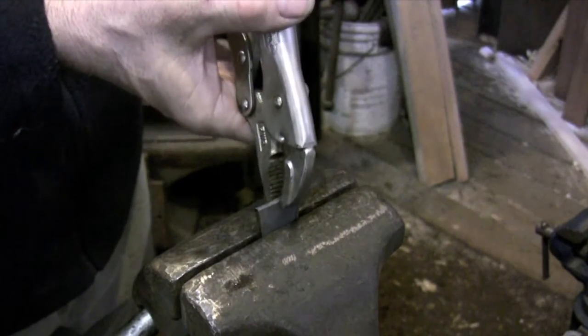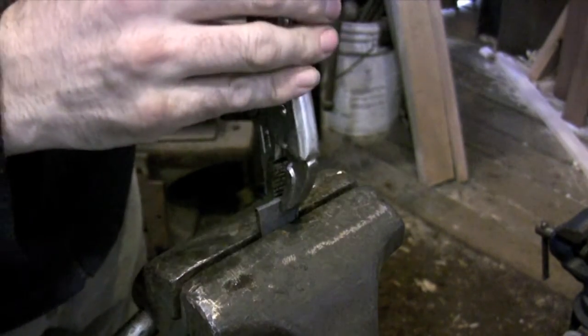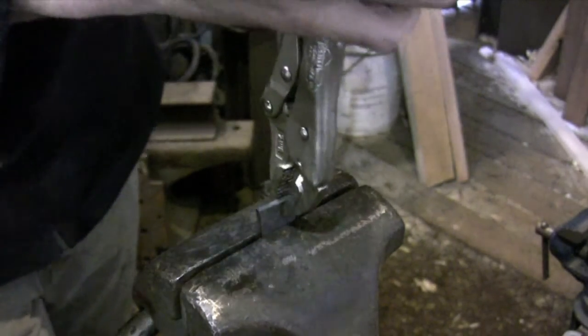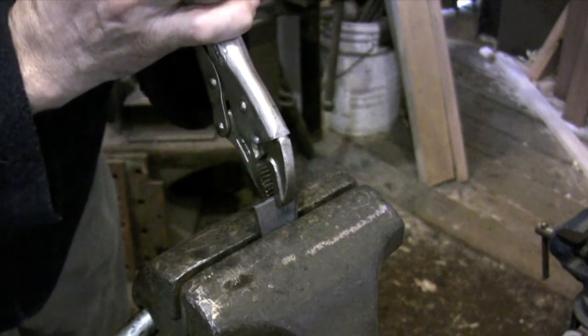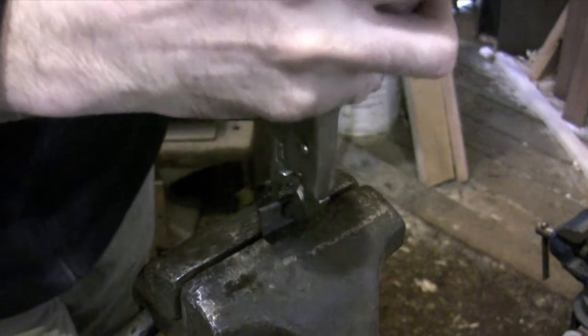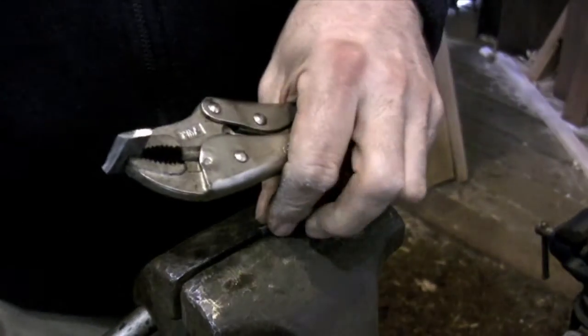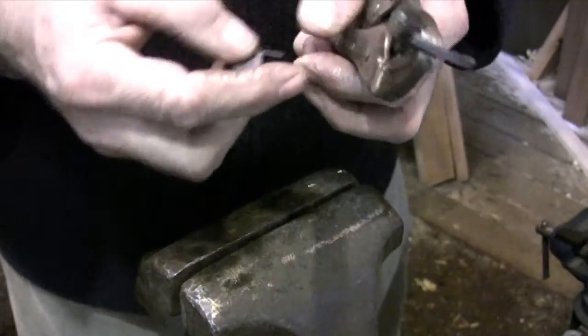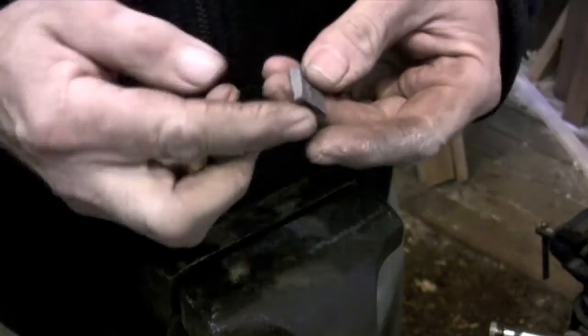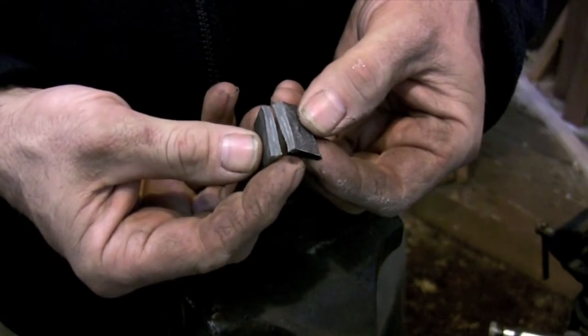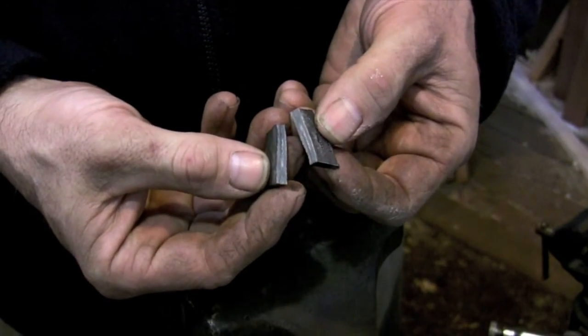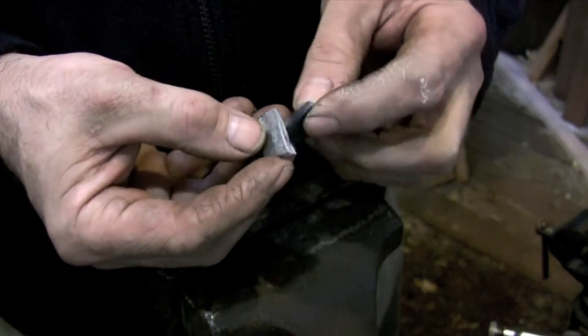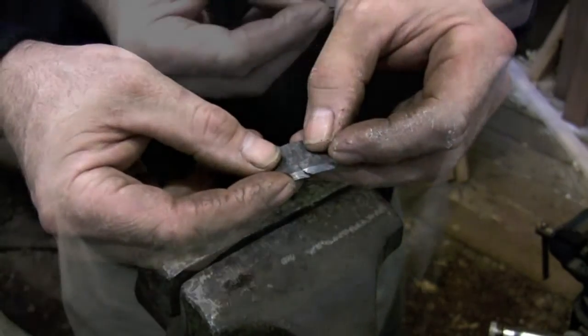The second sample piece with two forge welds offers quite a bit more resistance. The weld is actually strong enough that I need to bend the sample before the weld will break. But like the first sample, it breaks cleanly along the weld line, and it's obvious that the welding process hasn't been completed. So even though this would be considered a very serviceable weld today, and certainly more than adequate for any decorative purpose, it's important to understand that the weld still needs more time at a welding heat to reach its maximum strength.